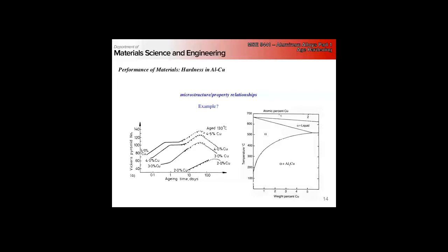Well, we know in aluminum copper, our primary reinforcing phase at peak age at these temperatures is going to be theta double prime. So here's GP zone formation. GP zones have saturated, formation of double prime, they're growing, and at the same volume fraction the particles are going farther apart. Peak aged is where it's equally hard to loop around and to cut the particles. Why with 2 and 3% copper do you just have one slope? Is it because you're fully within the theta double prime region?